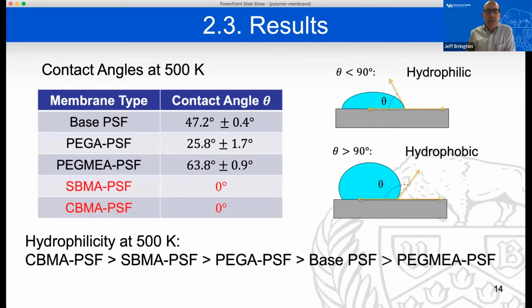If we translate this into quantitative numbers, the base PSF membrane has a contact angle of around 47 degrees. The PEG A1, 25 degrees, and the most hydrophobic system is that with the PEG MEA, which has a contact angle of 64. So this PEG MEA, you may have noticed before, has a methyl group at the end. And so qualitatively, one can understand how that system may be a bit more hydrophobic in nature. So the hierarchy in terms of the wetting characteristics that we would conclude is you have the two zwitterionic ones, and then as you go from left to right here, the system becomes more hydrophobic in nature.